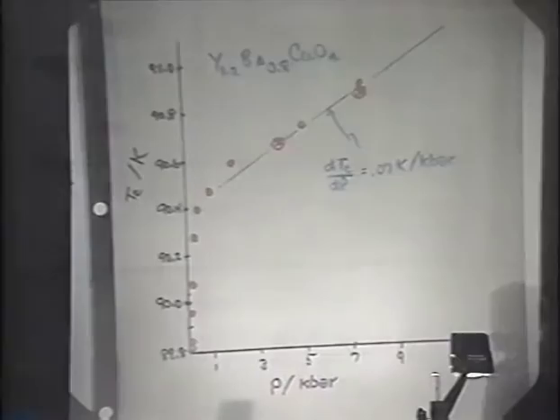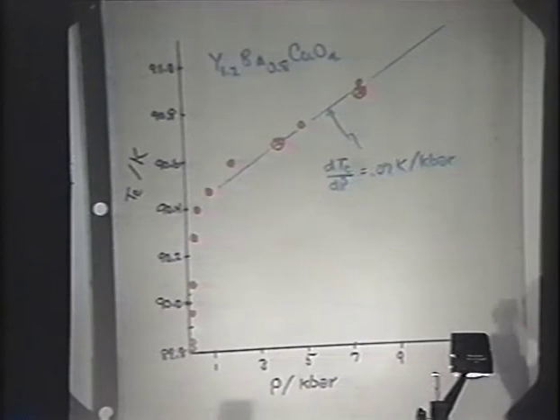Now, that's as opposed to the system we're going to talk about now, where we really have just an indication this is going on, but I think it's extremely provocative, and I'm convinced that it's happening. This is a measurement of T sub C. This particular foil is the Chu composition, but we've also done it in the 1, 2, 3 composition. A plot of T sub C versus pressure up to about 10 kilobars or 9 kilobars.